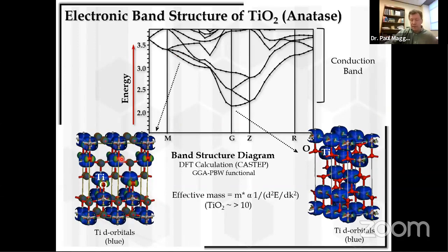And so this is one of the reasons why the carrier mobility in TiO2 is so great, and it actually has a great mobility for the carriers to reach the surface and drive water oxidation or water reduction. In this case, it would be water reduction, right? Because this is the conduction band. Similarly, I could have shown the valence band as well.